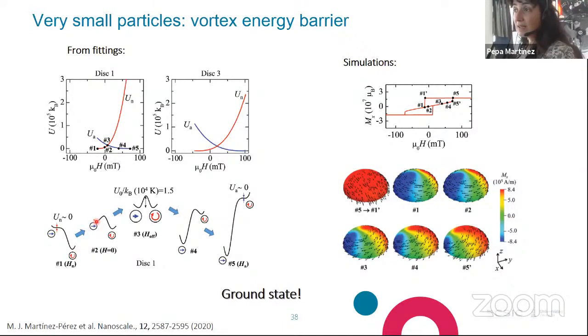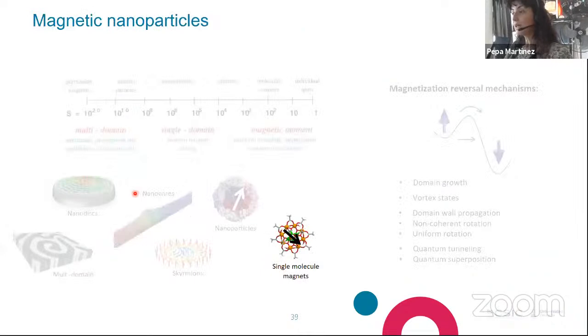Estimating the values of the energy barriers separating this vortex and the single domain states, thanks to the temperature dependent measurements, we could verify that at zero applied magnetic field, the ground state of the particle corresponds to a vortex state, with the single domain state being metastable. This is important because these particles are probably the smallest particles in which a magnetic vortex has ever been stabilized as a ground state.